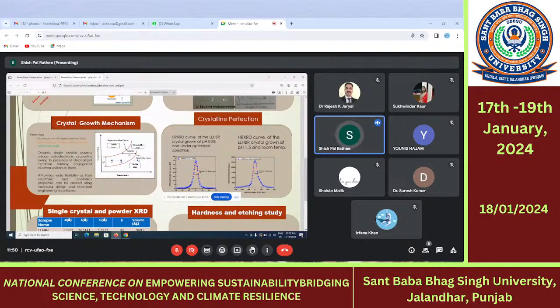And further, here we can also assume that the change in value of pH absolutely affects the growth quality of the crystal, and the main parameter is that the value of pH also controls the nucleation of the atoms or molecules in the solution. And further, we can say that the value of pH will also increase the induction time period of the growth of the crystal.